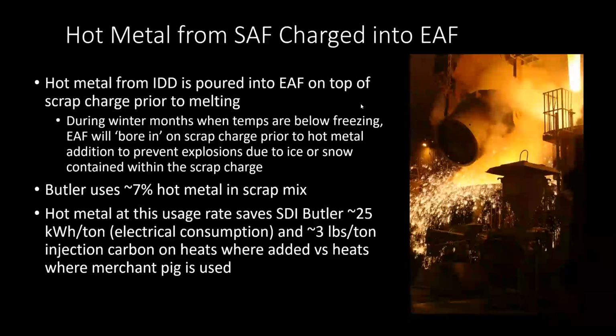One quick note about using hot metal, this is kind of a safety note. As you pour hot metal in the winter months, one thing we do is what we call a bore and pour practice. If the electric arc furnace might have ice or snow or frozen water in it, we'll put a couple megawatt hours of electricity into the furnace, then open the roof and pour liquid on it. Yes, that slows our process down a little bit, but we've had some bad scrap type explosions pouring hot metal onto scrap with ice in it. So it's just a safety precaution now that we don't do that anymore.